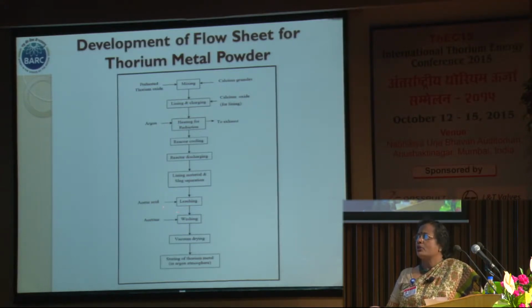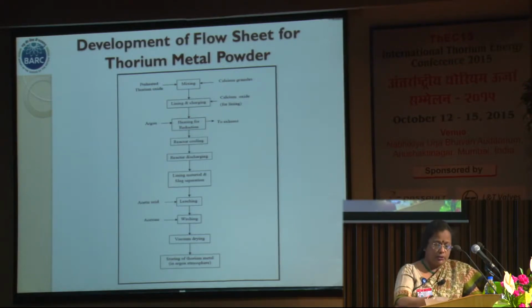The basic changes were these. The leaching process was done with acetic acid, where our losses have been reduced, and impurity content and oxidation problems have also been reduced. After leaching with acetic acid, the metal was washed with acetone. After vacuum drying, we store it in an inert atmosphere. This gives around 99% purity, which can be used as commercial quality, but not for thermodynamic studies. But we wanted to use it for alloy preparation for the fuel, so for us it was good enough.